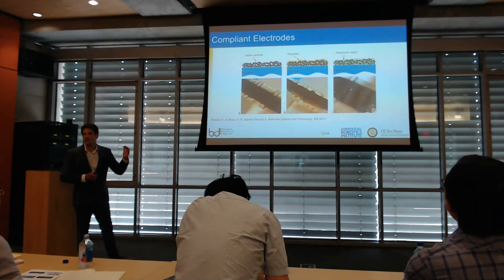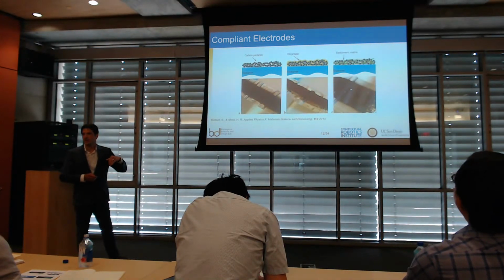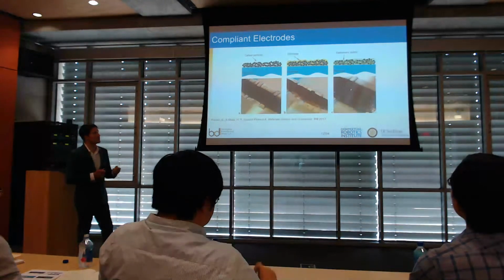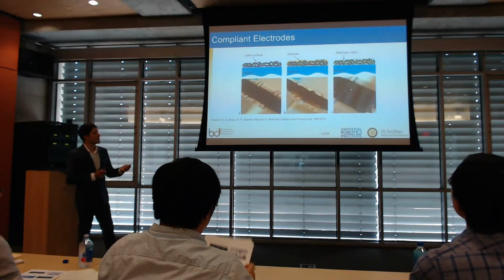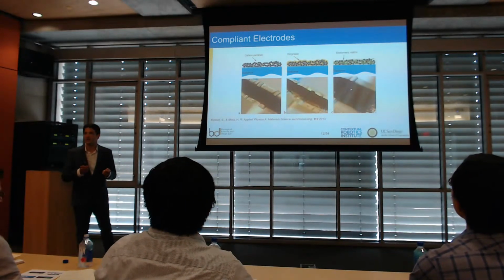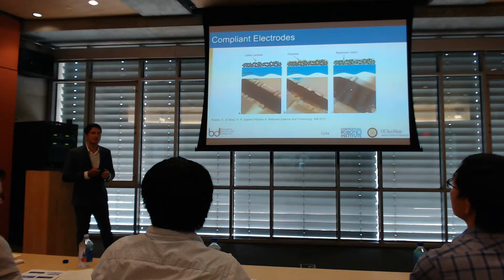But the trouble with the grease is that it will actually permeate through the elastomer and change the mechanical properties of the elastomer over time. And then other people will use an elastomeric matrix. But the trouble with the elastomeric matrix is that it can also stiffen your actuator, so you can get less performance within the structure.